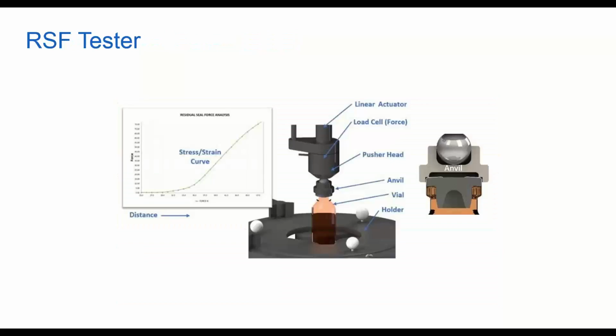Go ahead, one more. So this is an illustration of how residual seal force is measured. You can see it looks somewhat like the capping device we saw a few slides ago. But essentially what we do is we apply a load to the vial, and by applying that, we measure it using a load cell, and we create a stress strain curve. You see that to the left. And if we analyze that stress strain curve, go ahead to the next slide.